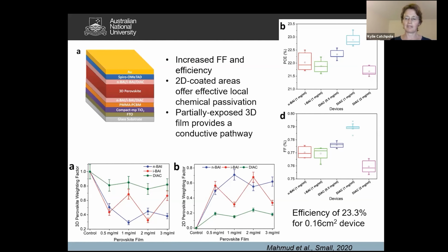And again, what we see in this case is you have a significant improvement in fill factor, and as a result, a significant improvement in the efficiency. And in this case, we had an efficiency of 23.3% on a small device.